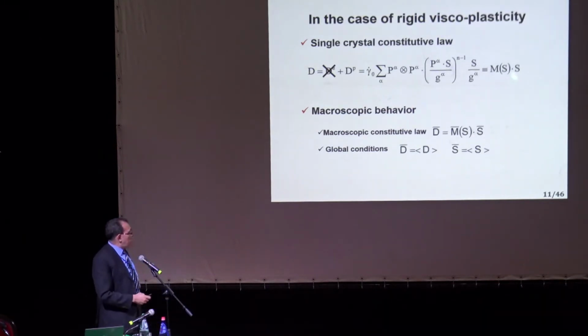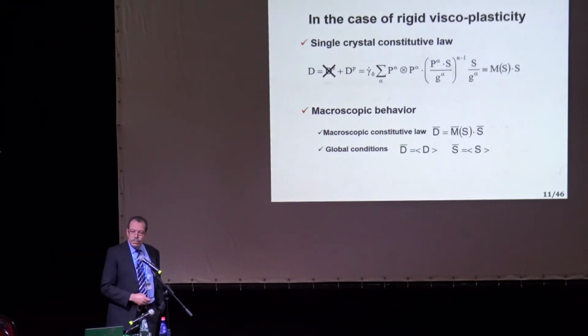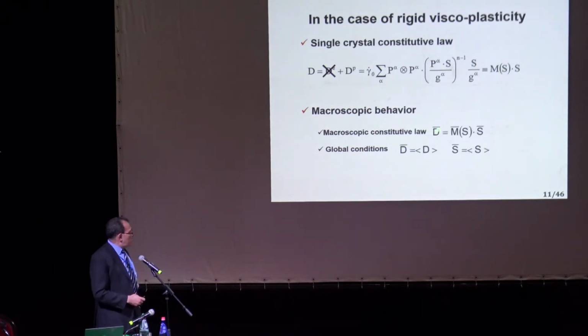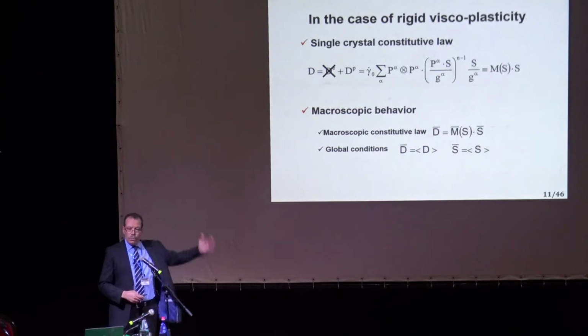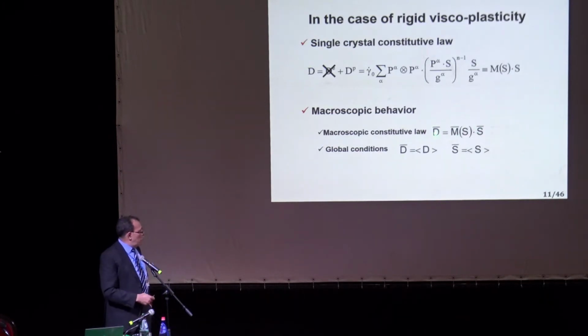Now, I have a constitutive law at the single crystal level. And then we assume at the macroscopic level for the polycrystal a similar relationship. M bar is the macroscopic compliance tensor, S bar is the macroscopic stress, D bar is the macroscopic strain rate, and then we have to make sure that the global conditions apply, that the averaging conditions, the macroscopic strain rate matches the average of the local strain rates, and the same thing for the stresses.